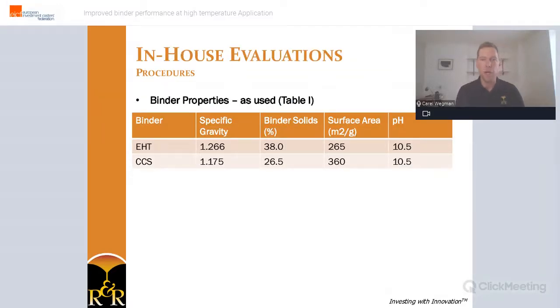The properties of the binders we used to build the backup slurry were as follows. The CCS binder has a typical particle size of 10 nanometer and a silica content of 31.5%. But in this comparison, it was diluted with water back to 26.5%, a level that is more commonly used in commercial foundries. EHT has, compared to the CCS binder, a higher specific gravity and binder solids percentage, and also less surface area.